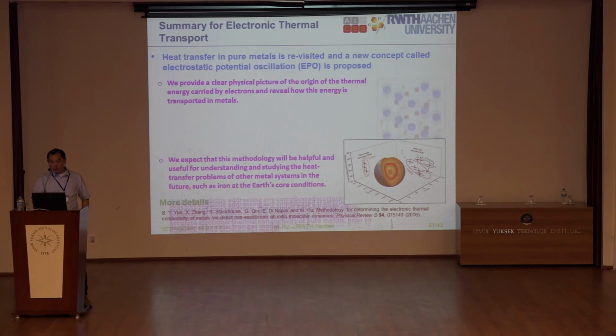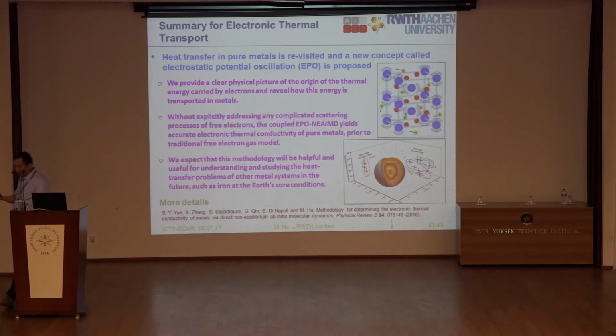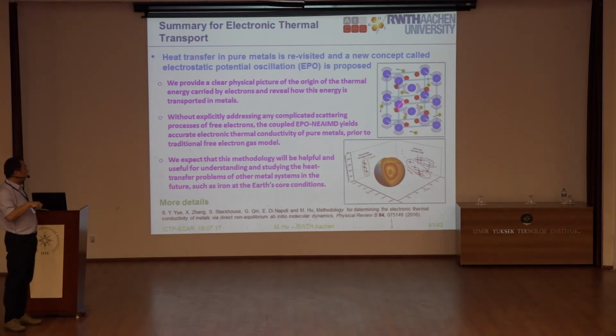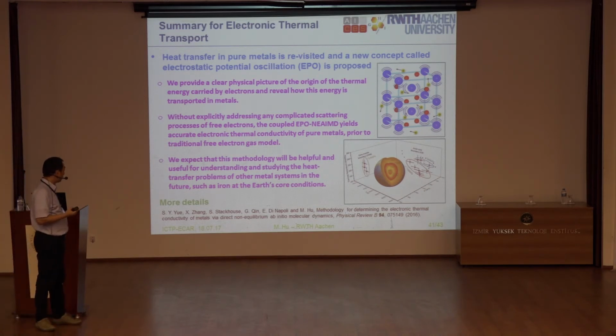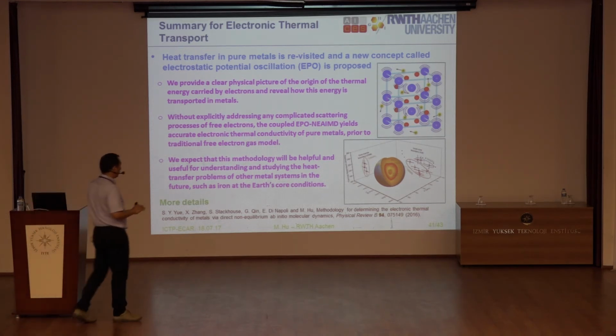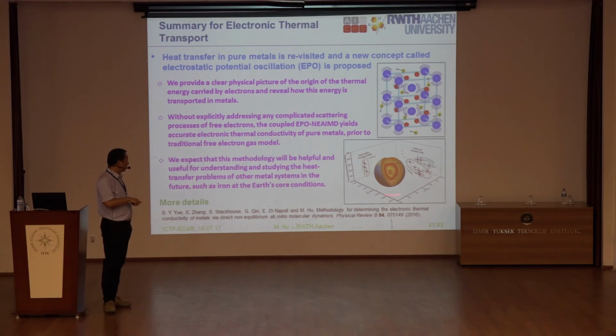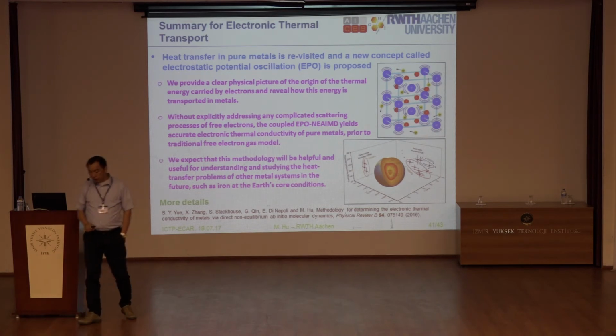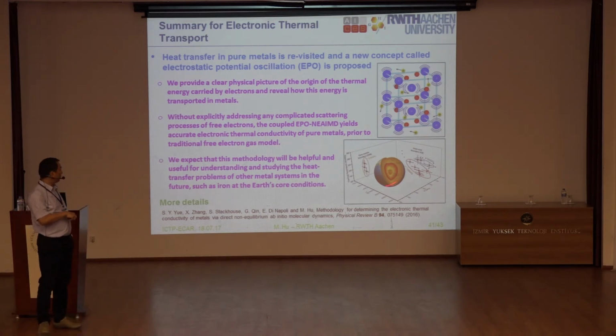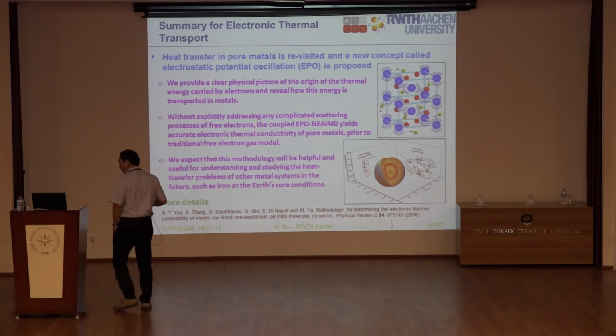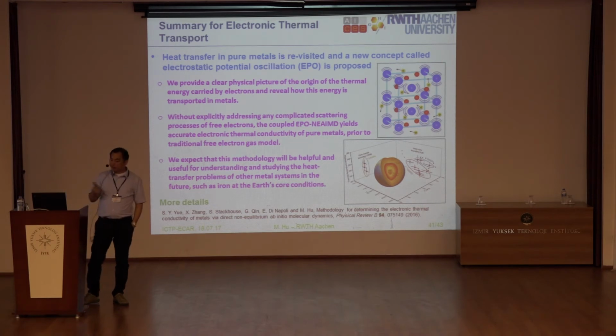Okay, so to summarize this part, we have proposed a new concept called the electrostatic potential oscillation. Based on this EPO concept, we calculate the electronic thermal transport by direct ab initio molecular dynamics simulation. And then we can calculate the thermal conductivity of some pure metals very well, and agree with experiments very well. And in recent days, we apply this method to the very high temperature, high pressure phase of iron in the Earth's core conditions, because, as I just mentioned, such conditions cannot be easily done by experimental study, because you have to apply very high temperature and pressure. So we are trying to explore what's happening there and what exactly the thermal conductivity of iron is at such extreme conditions.